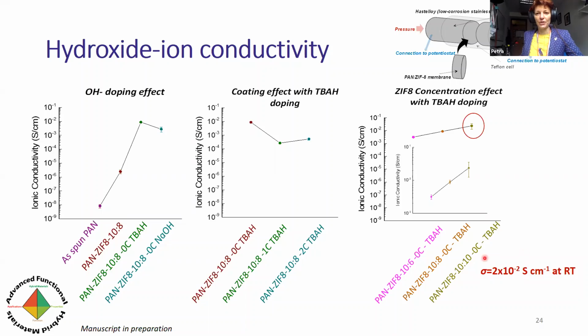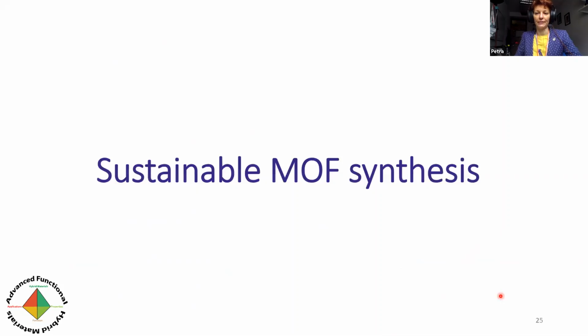And at room temperature, this is at the moment a record-breaking hydroxide ion conductivity for metal organic frameworks, at least. In fact, by about an order of magnitude. So we're quite proud of it. And it's also a higher hydroxide ion conductivity at room temperature than is known for Nafion. And of course, this is a not very optimized synthesis.